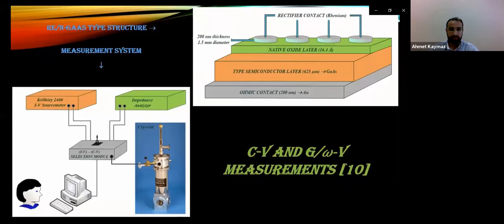To obtain CV data at 1 MHz frequency, a Hewlett-Packard impedance analyzer was used. The schematic diagram of the measurement system can be seen in the figure. As seen in the figure, the measurement was carried out in the cryostat to eliminate the external effects and noises.